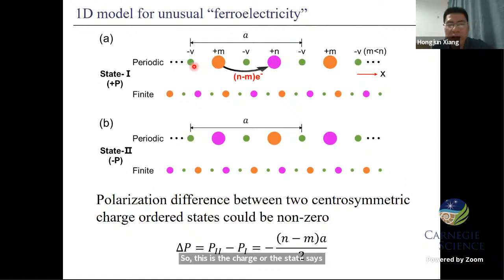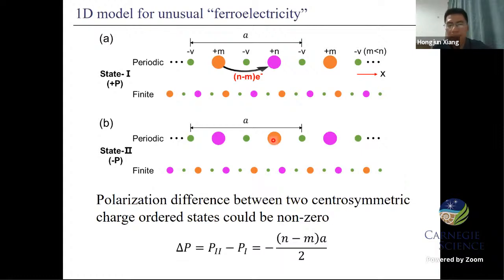In this 1D structure, this is the charge order state system. This is the anion site, and these two are cation sites, but they have different charge states: -v, +m, and +n. We call this state 1. We can see this kind of structure has inversion symmetry. This is the inversion center, and this is the inversion center, right? Another state we call state 2. The difference between state 2 and state 1 is that the charge order sites are switched. For example, this becomes +n, and this becomes +m. Both states have inversion symmetry.